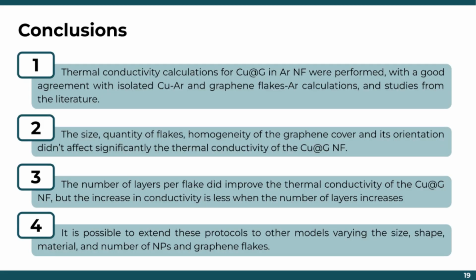In conclusion, the developed MORSE potentials are able to reproduce the structural behavior of the copper capped by graphene nanoparticles and are useful to calculate the thermal conductivity of copper capped by graphene in argon nanofluids. These results are in a good agreement with calculations carried out for copper nanoparticles in argon and graphene flakes in argon, and with the studies already reported for these materials separately.